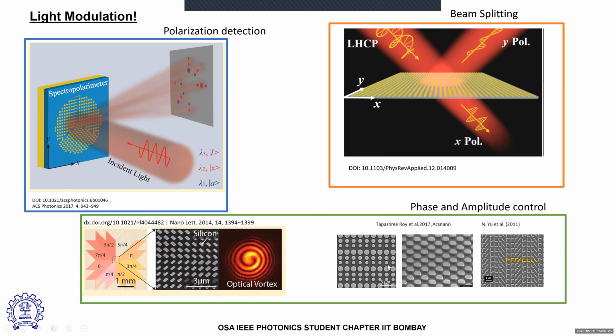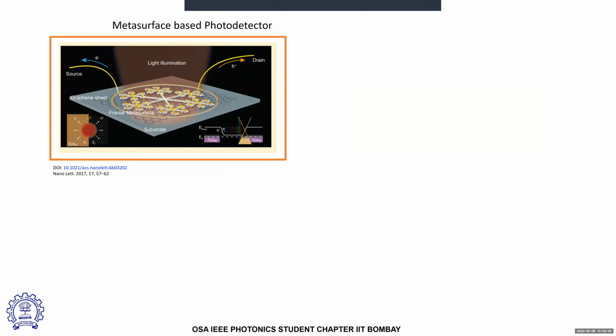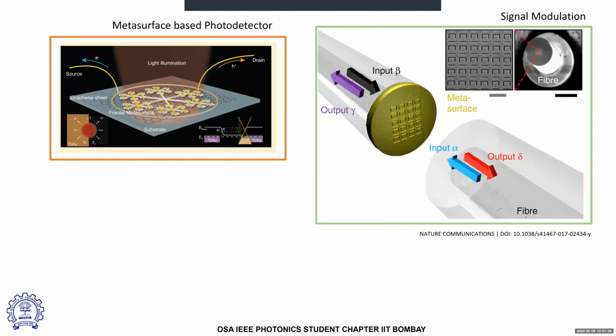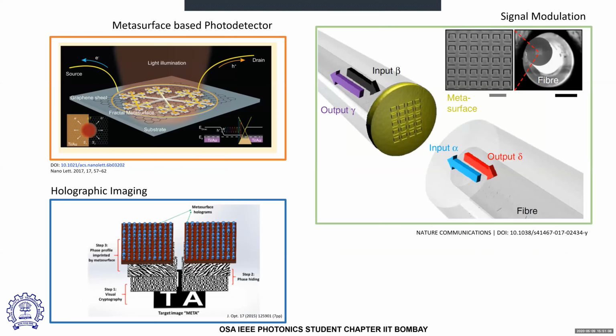Then again, we also have different sizes of these nanostructures. Instead of having just rectangles, you can have meta atoms or meta molecules, where you can have two structures or three structures in a single unit cell. Changing the dimension in a single unit also introduces some kind of phase and amplitude modulation into the reflected beam, which can be used for vortex beam splitting and polarization detection at the same time. Then also meta surfaces have been used for enhancing the efficiency of other devices, which could be based on photodetectors, modulation of the signals in optical fibers, or holographic imaging. So in all three cases, we have different types of interaction of meta surface with different devices.